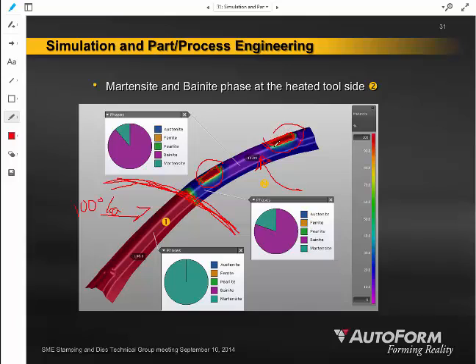And where the blank was resting on this tool, it was acting as a heat sink, and it was drawing that heat out of the tool at a faster rate than did the rest of this A-pillar, where we have some ability to put cooling channels or heating channels through the die in order to maintain the 400 degrees Celsius temperature. So the rest of this A-pillar was being maintained at 400 degrees C, except for the little spring-loaded pads that were controlling this blank's orientation during the loading.